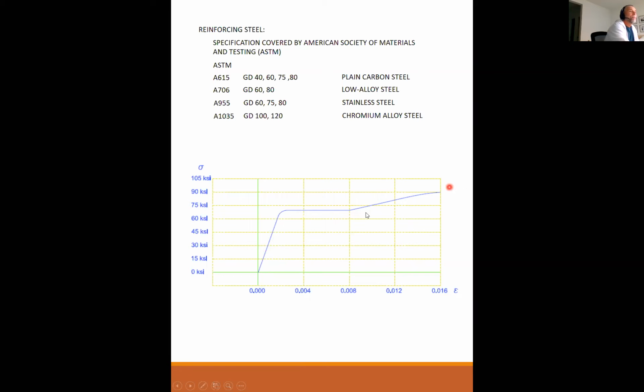This is very typical of what you might see for a real rebar test. The minimum specified for 60 KSI is here. This is 60 KSI. This particular one might yield at 72 KSI, which is perfectly fine. As long as it yields at or above the specified 60, then it meets the criteria for the rebar. And so this is what it might really look like. The red line is how we're going to design it.